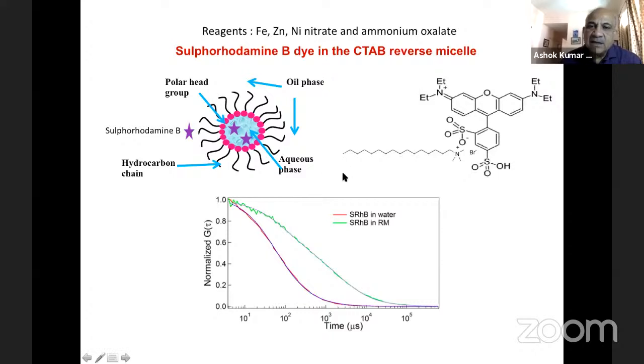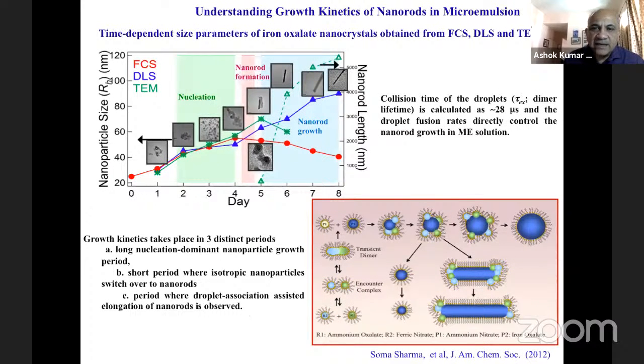So this is how FCS gives data, and you can simply see that if you put the dye only in water, then the relaxation is very fast, whereas if you put the dye inside the droplet, then it is slow. And so you can understand the dynamics of the motion of such particles using the fluorescent probe. Using that, this is the result.